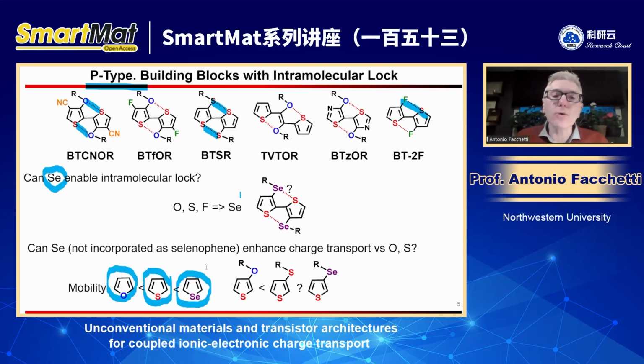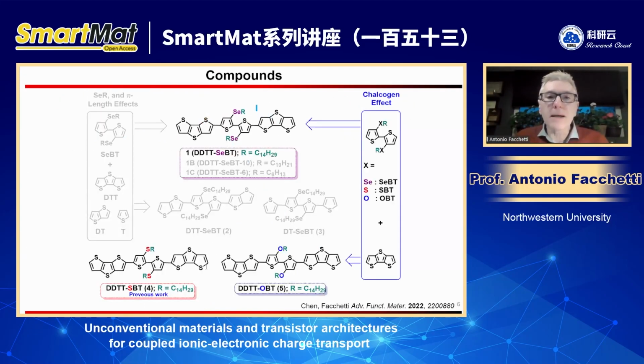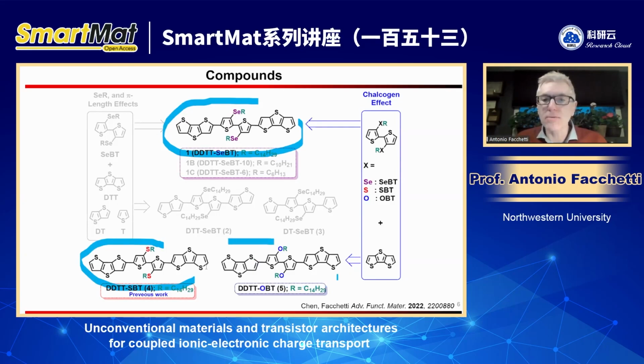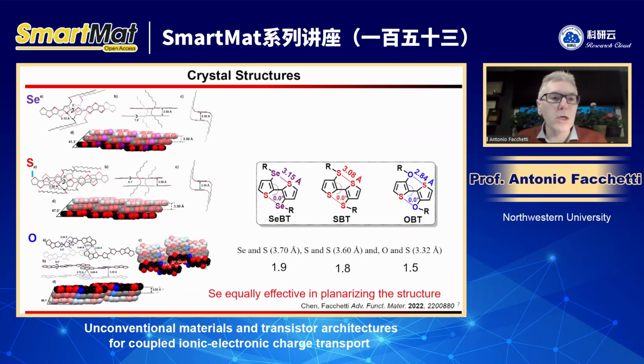To answer this question, we made a lot of molecules. I want you only to look at these three with the selenium, the sulfur, the oxygen. The first question is about planarity. So we made the crystal structure of all the three molecules. And what you see here, also in the case of selenium, is that the core is completely planar.